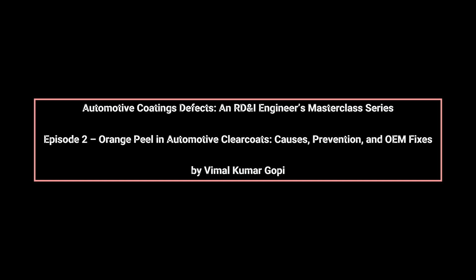Immediately upon application, the coating begins to lose solvent from the surface, while the internal film retains some mobility. This creates a gradient in viscosity from the surface to the interior, and if the surface forms a skin too quickly, flow from the underlying wet film is restricted.